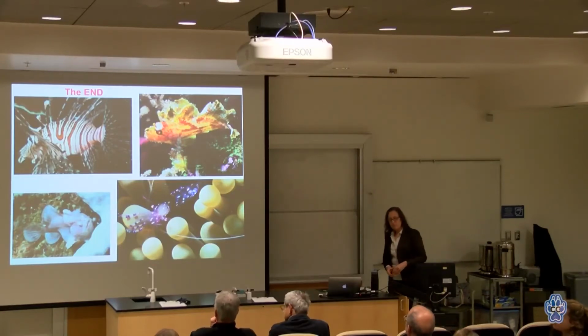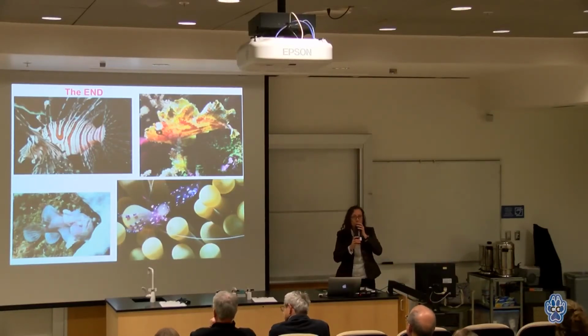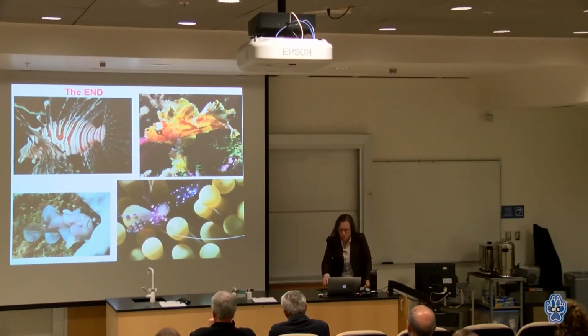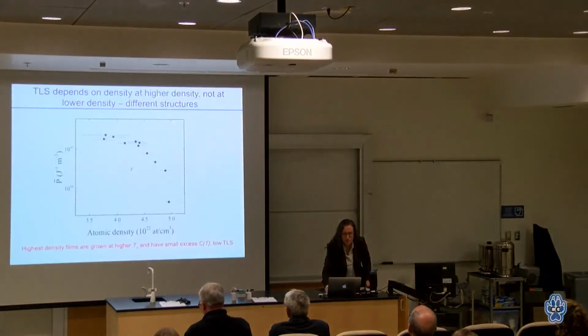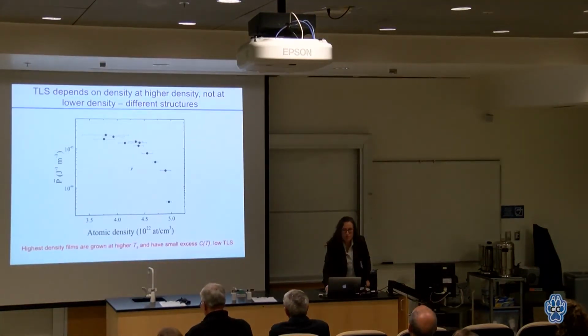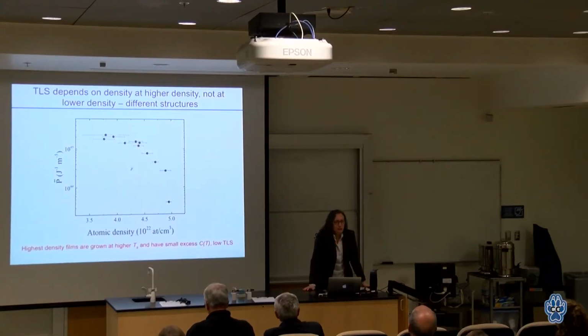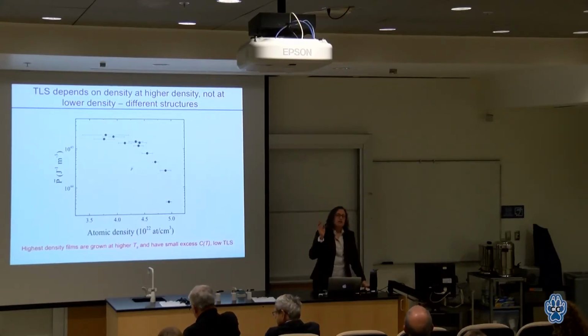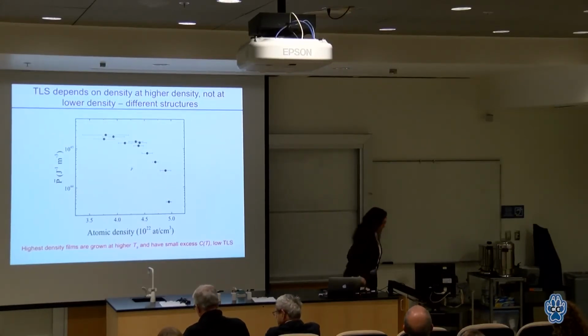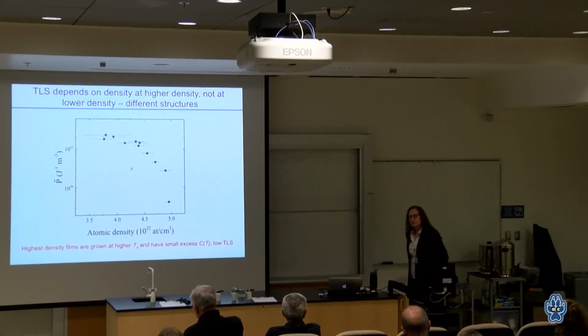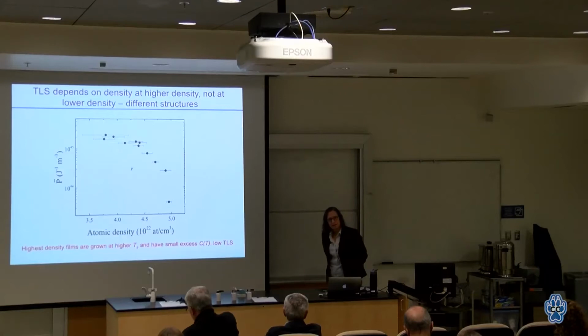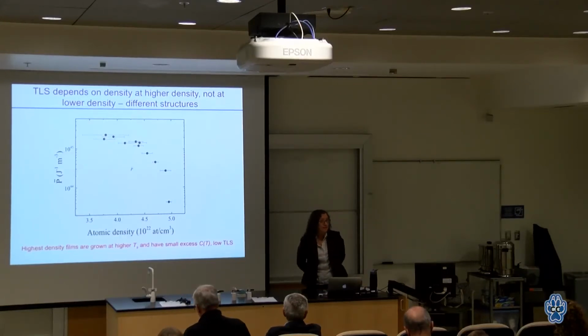You had a slide which showed the magnetic anisotropy from three samples, and I noticed that the growth rates were different. What happened to the total thickness of each sample? Did they have the same thickness, or actually different thickness? So there is a dependence. That density plot showed that the density depends on thickness. The magnetic anisotropy, to pretty good order, does not depend on thickness, but we mostly were only looking at pretty thick films back then. You notice there that we had no significant rate dependence, but that is on a linear scale. So again, there probably is a very small rate dependence also.